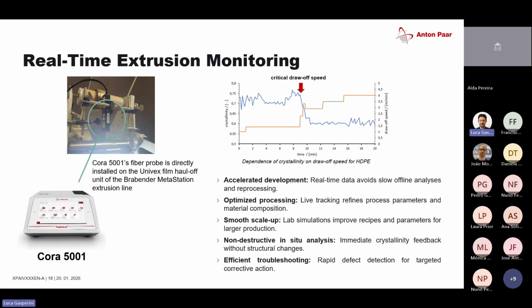So let's say you run an extrusion process and sometimes the crystallinity is very, very good. Sometimes the crystallinity is not within specs. Then this can be due to operating the extruder at this critical draw-off speed. So this is another application to show that just during extrusion, you can actually tell the crystallinity of your sample.